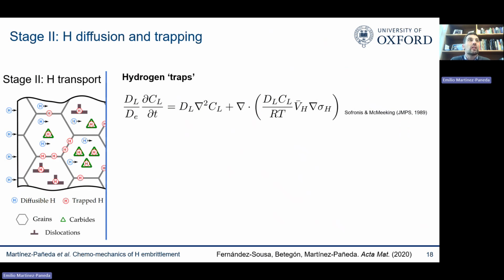Hydrogen not only travels freely through the crystal lattice, it's also sequestered at what we call hydrogen traps, so microstructural defects, grain boundaries, carbides, dislocations. And we can easily extend the model that I showed you before.